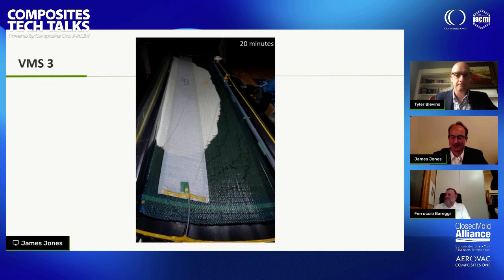Yeah, so tell us a little bit more about the VMS3. So as I was mentioning, and you can see from this picture, this is a spar that is a very critical part. It's a solid, extremely thick part made out of unidirectionals. As you can see here, we have the resin infusion line on one side of the part. The vacuum is granted only by VMS3 that is positioned on the opposite side. And specifically here, we have the infusion flow media, so the mesh, that is positioned between the mold and the part, so to have an impregnation from bottom to top.